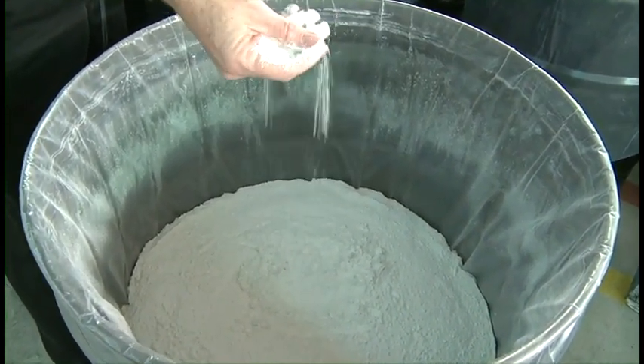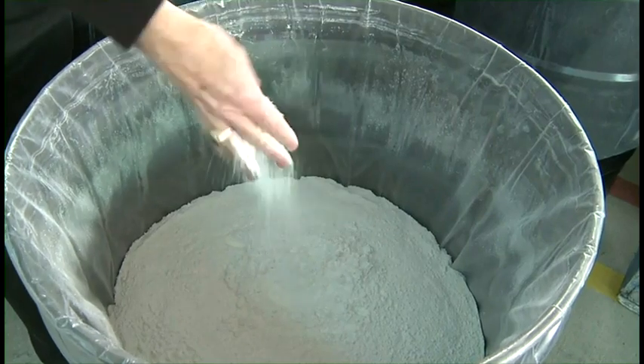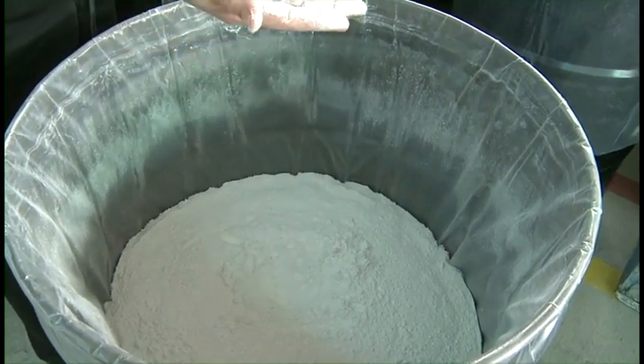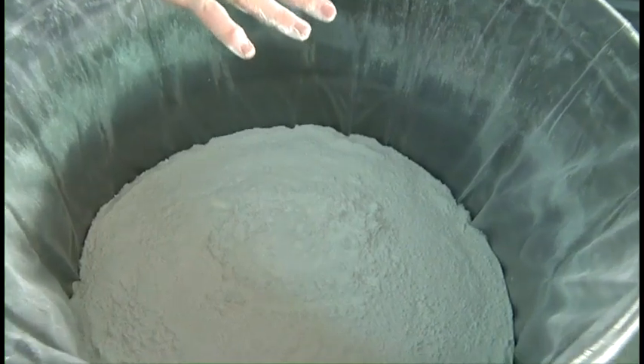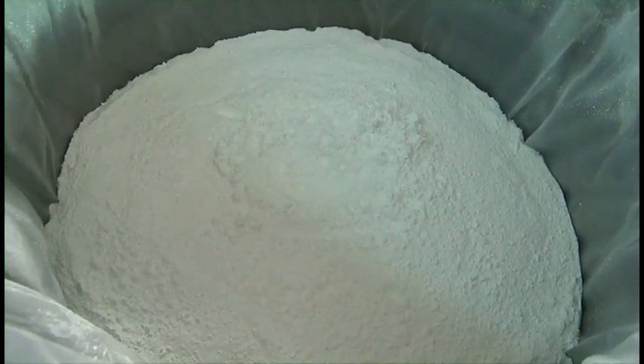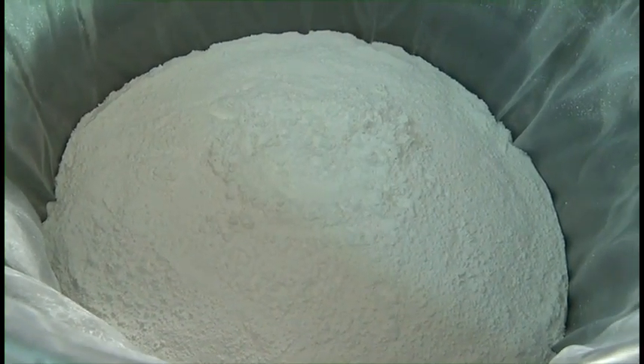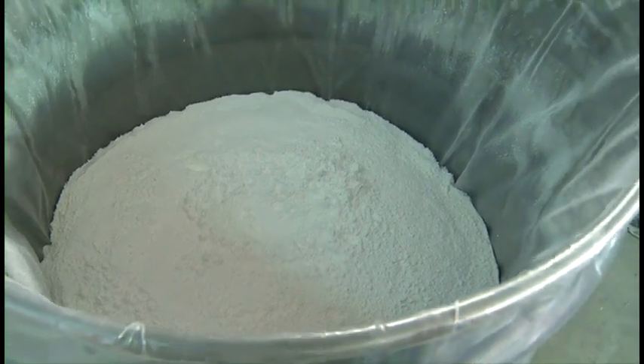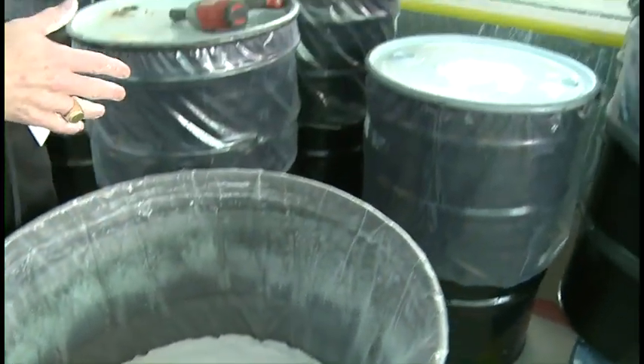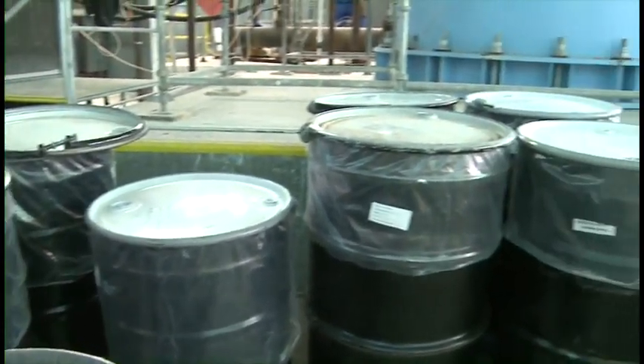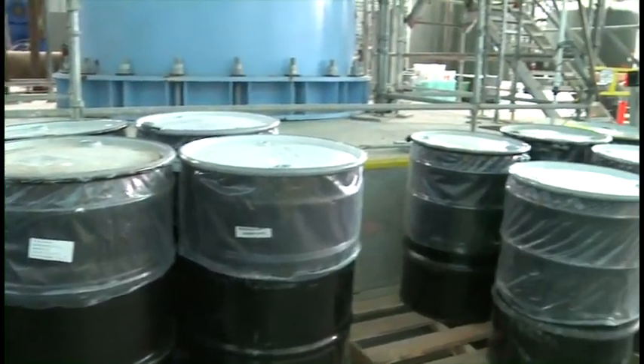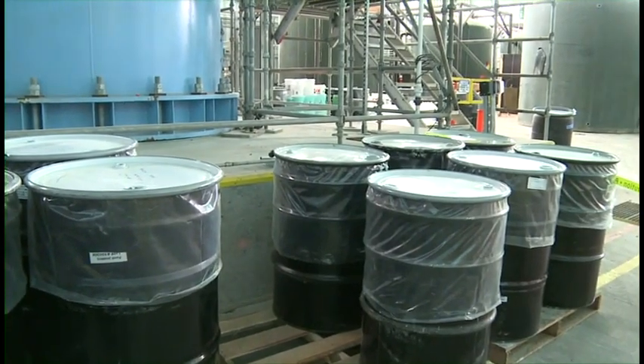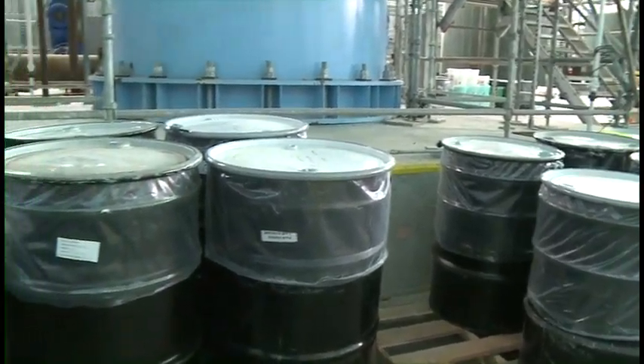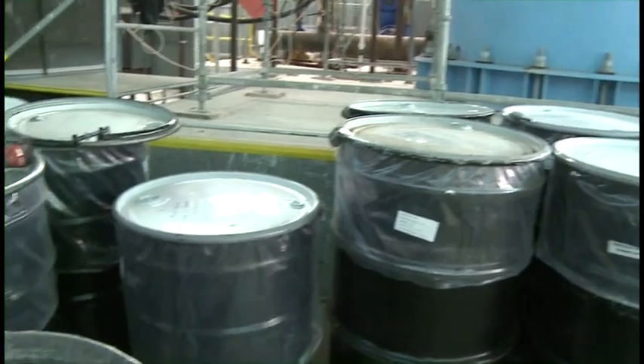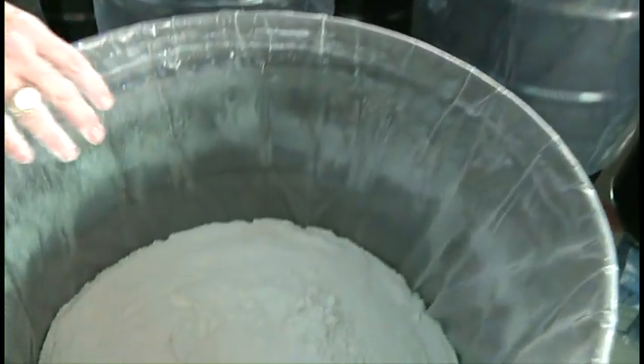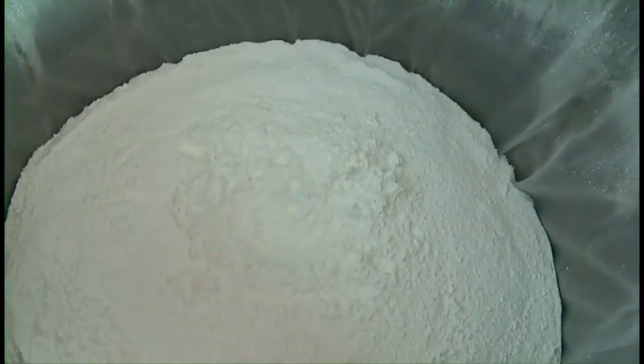Now this is carbon dioxide that's actually being sequestered in this final form. And that material can be used in cement. And in cement conditions, we have a very extensive laboratory where we mix these materials with ordinary Portland cement and can test their performance relative to other building materials. And we're currently meeting all of the ASTM 1157 standards for using supplemental cementitious material using these kinds of materials that we've captured.